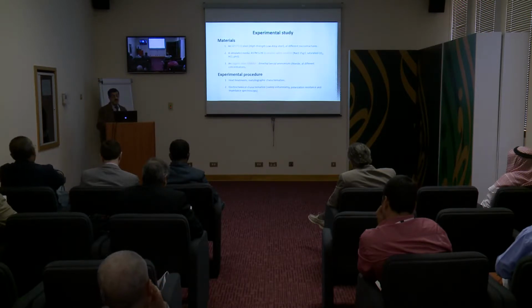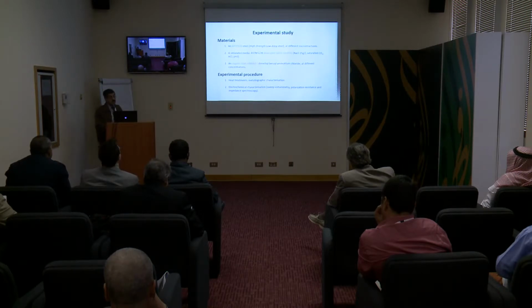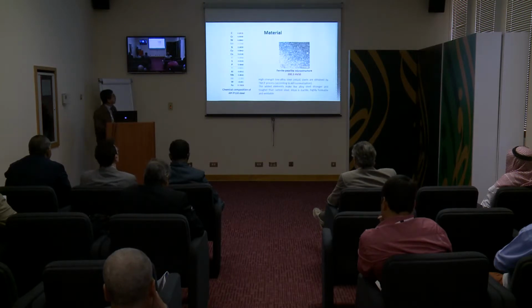The experimental procedure was to carry out some heat treatments leading to different microstructures and to characterize the metallographic situation, and after that to make an electrochemical characterization of the structures by sweep voltammetry, polarization resistance, and impedance spectroscopy. So our material, you can see here its chemical composition.